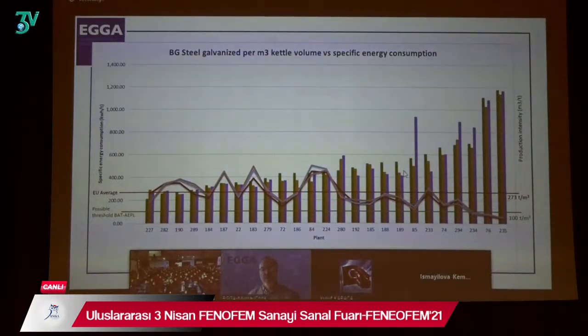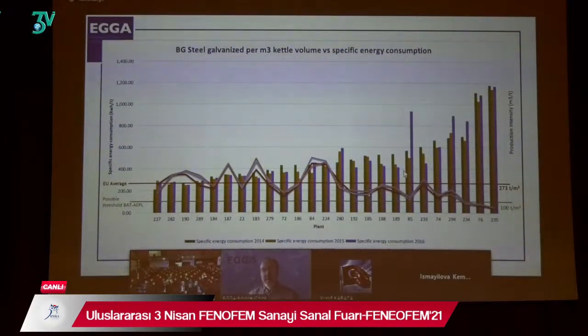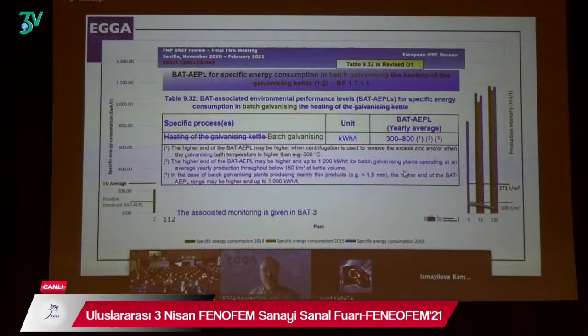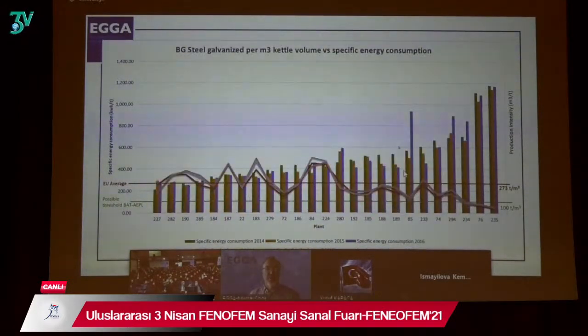And we had to work very hard between the industry and the regulators to recognise this point, using data, using information. And I can tell you that in the final version of, and you see this is from our working drafts from the European Commission, we had initially a limit, or a guidance limit, of 300 to 800 kilowatt hours per tonne. This was the conclusion coming only from the data. You can see 300 is somewhere around here, 800 is here, and you had some plants which are above 800. And the reason these plants are above 800 is because they have a very low level of production for the size of their plant.